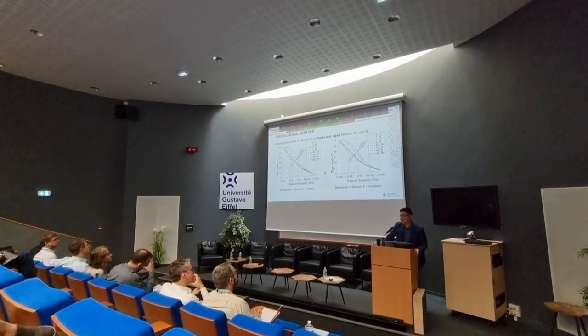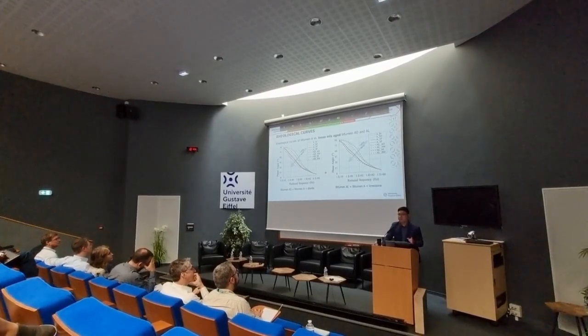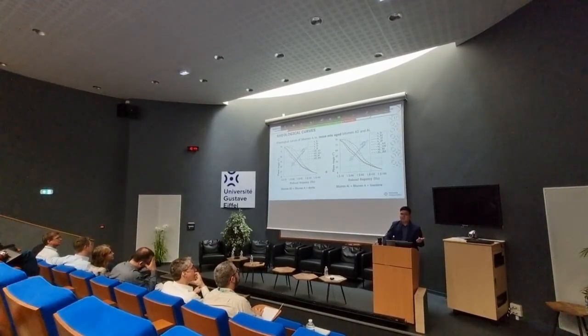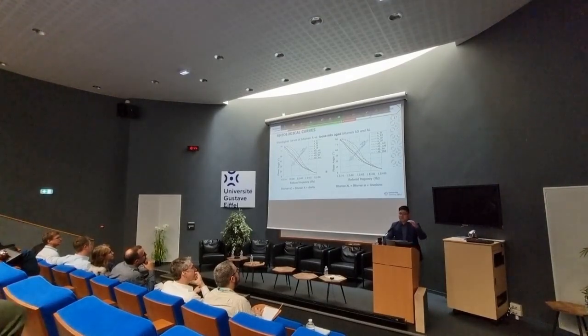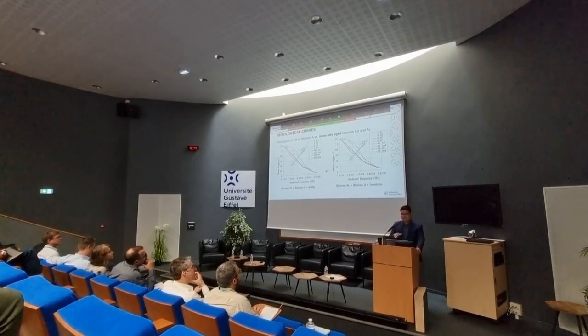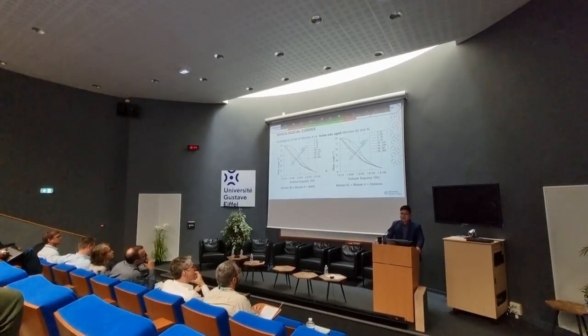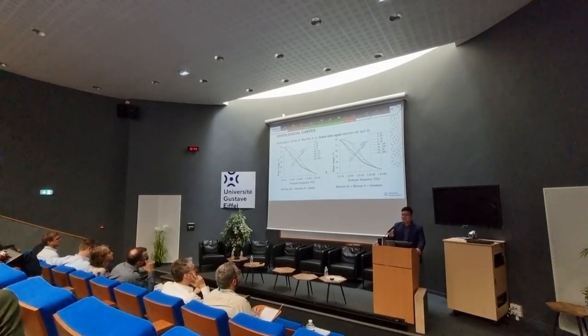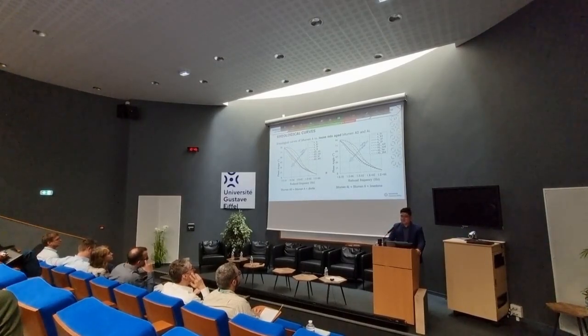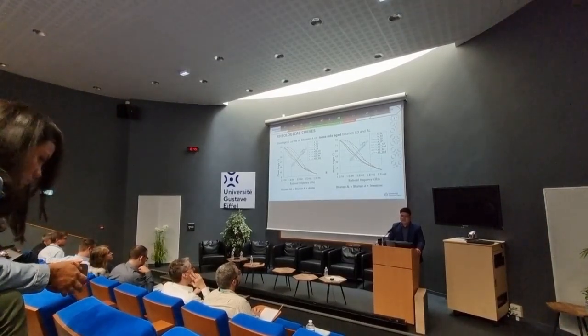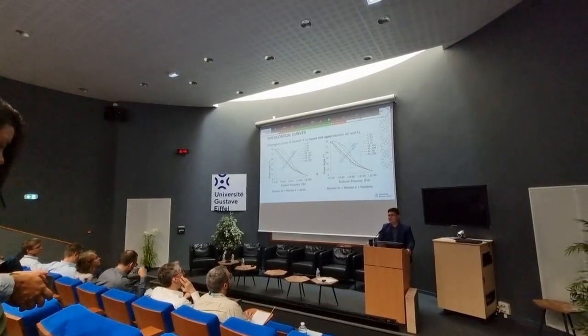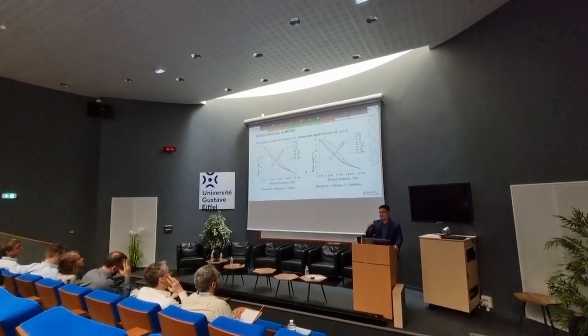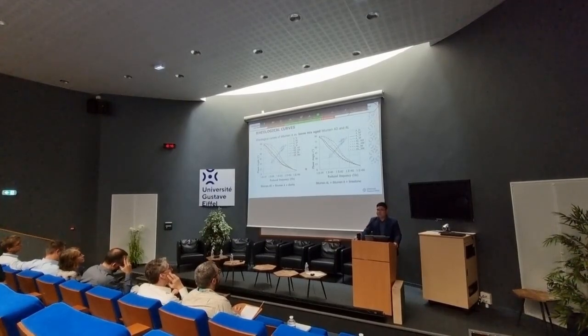But when we look at the experimental data that was measured at the same frequency and temperature, we saw an overall reduction in the phase angle in all these conditions, at least with our materials, which is why we could conclude that the only thing that changed was aging. But you're also right about the shifting factor and the master curve construction, because it's highly dependent on the shifting factor method that we use. This could flatten our curve more or less. We could also have a steeper curve. So I agree with you.